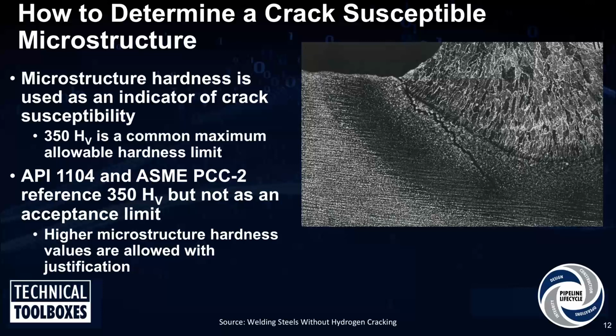But in this situation, it's similar to burn through risk and wall thickness. Thinking if you draw a limit, if you're over that limit, you're fine. If you're under, you have a concern. Well, from a hardness cracking standpoint, yes, you can have this 350 Vickers hardness limit, but you're allowed to have welds that are higher hardness and still acceptable as long as you control the other factors of hydrogen cracking, which is hydrogen content and stress. So if you go use low hydrogen welding electrodes, again, you can have a weld hardness that is over 350 and it still will not crack.